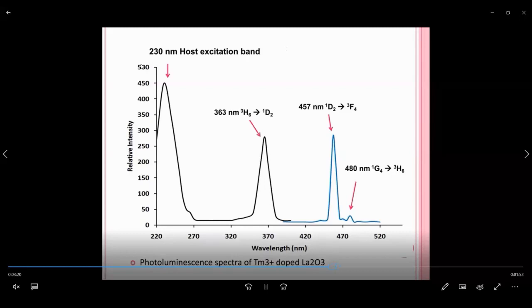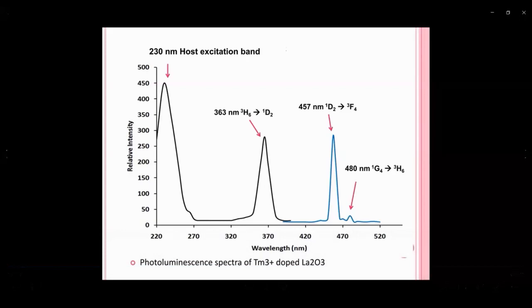The blue curve indicates the emission spectra of the prepared phosphor. It shows the main emission peak at 457 nanometer. It is due to the transition from 1D2 to 3F4 level of Tm3+ ion. And there is an additional small emission peak at 480 nanometer. It is attributed to the transition from 1G4 to 3H6 level of Tm3+ ion.